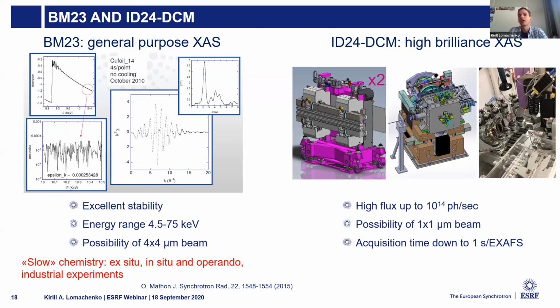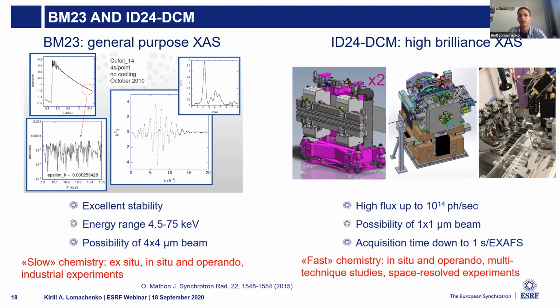The goal is to reach an acquisition time of 1 second per EXAFS spectrum, so every second we can measure a high quality EXAFS that can be analyzed by itself without further averaging. We are pretty confident we can reach this goal. This beamline will be used for fast chemistry, in situ and operando, for multi-technique studies - we'll have possibilities to do XRD, XRF, X-ray emission, infrared, and mass spectrometry there. So it will be a very versatile tool for chemical studies.